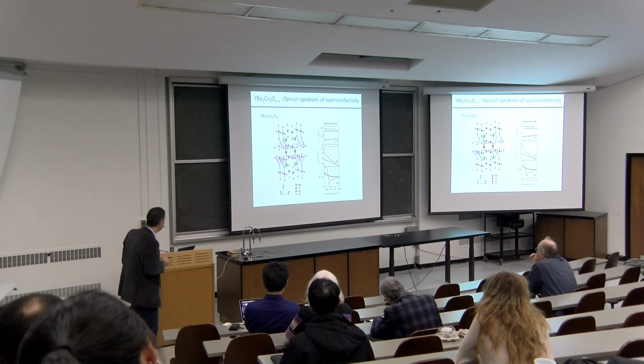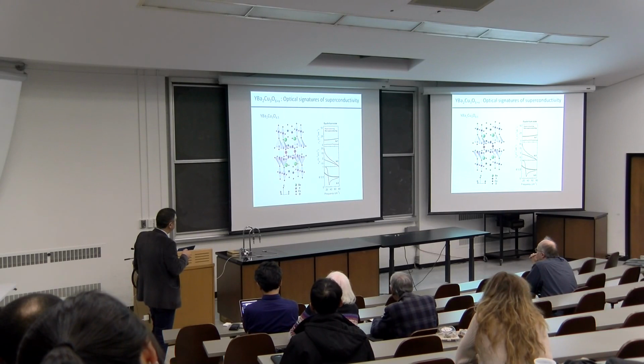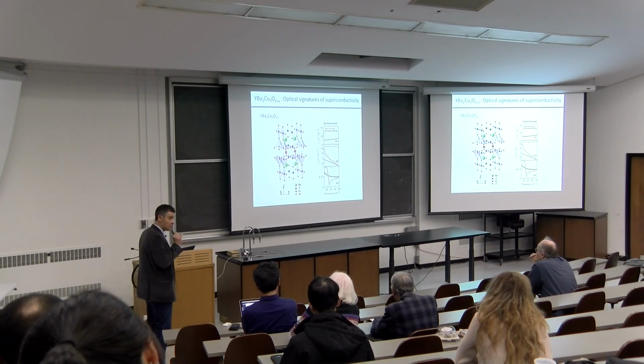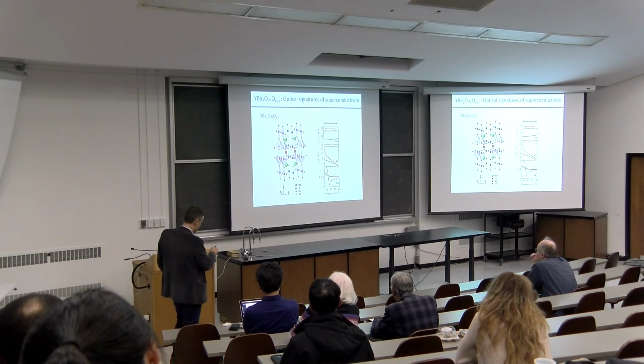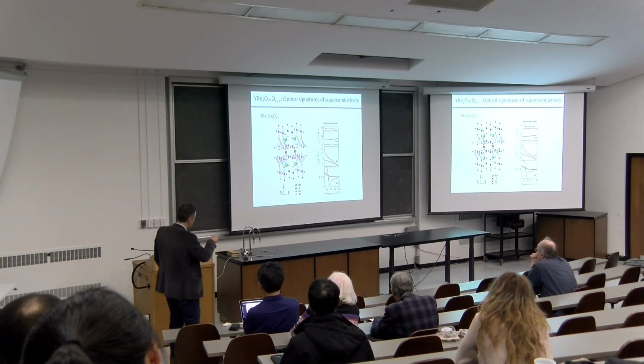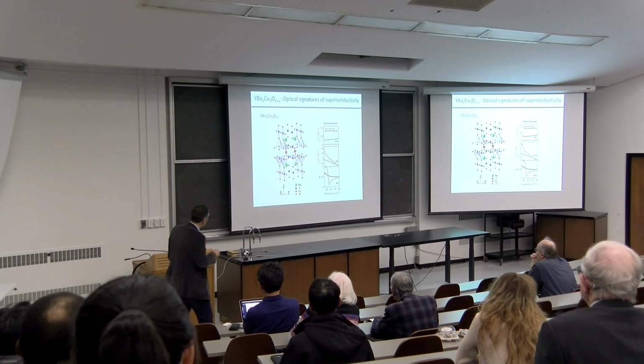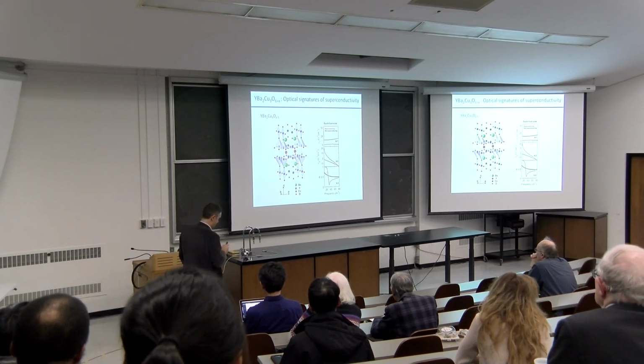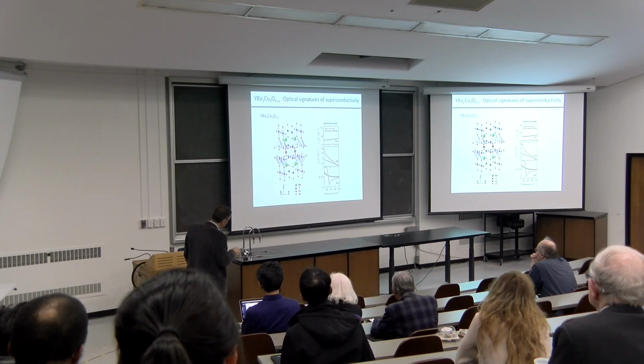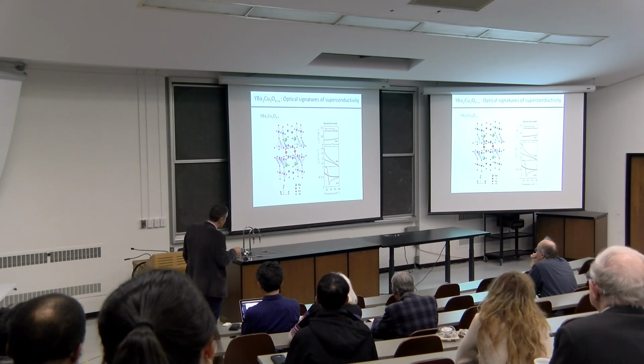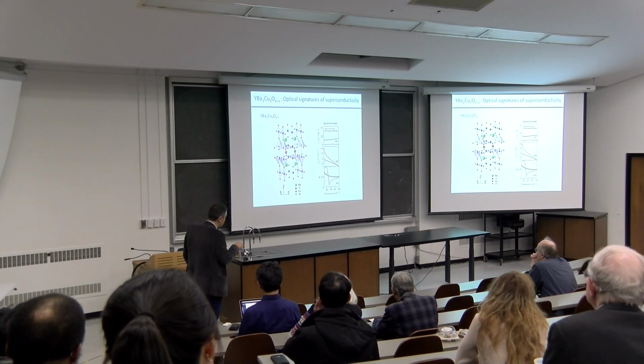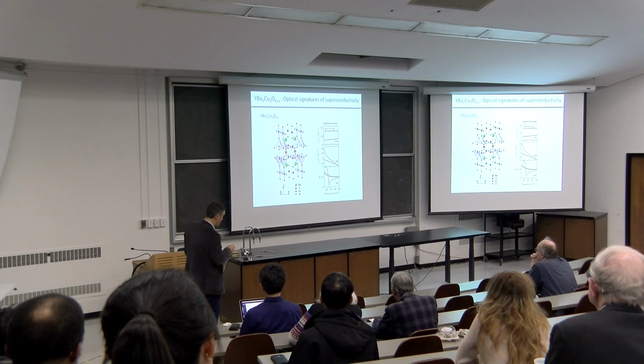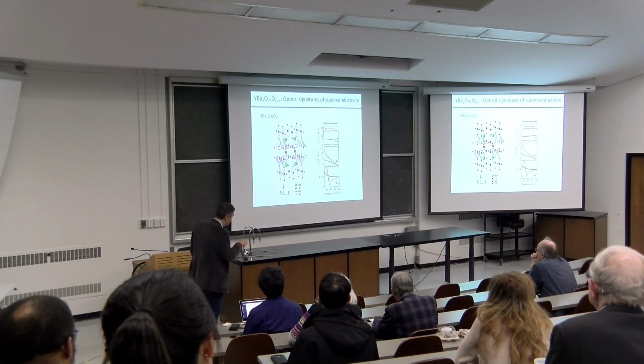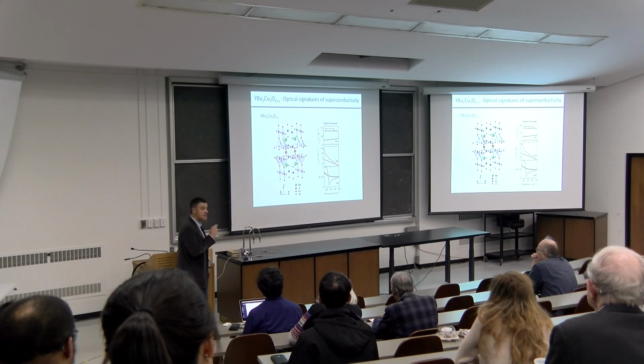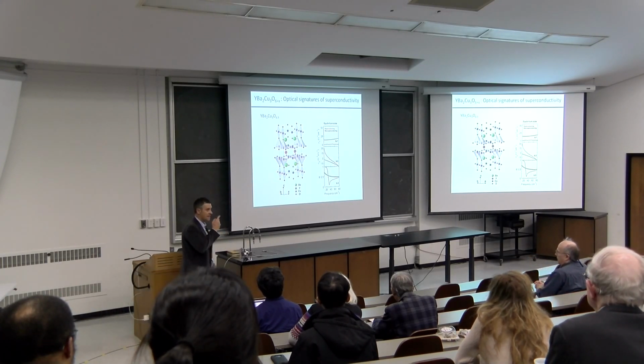So if I look at the optical response of a superconductor in equilibrium below the superconducting transition temperature at long wavelengths, so this is 1, 2, 3 terahertz, for light with the electric field polarized perpendicular to the superconducting planes, what one finds are a few key features. Here I'm plotting the reflectivity as a function of frequency for this material above and below the transition temperature. What one observes below the transition temperature is the appearance of basically a plasma edge. It's the same thing that you see in a piece of, say, copper at 2 eV.